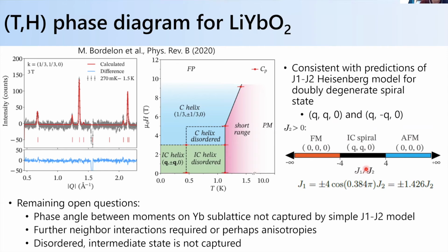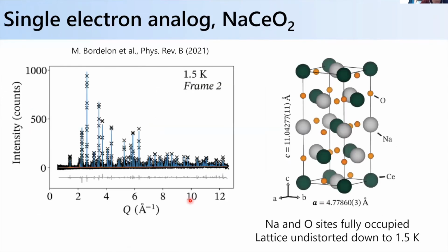And so in this regard, since we know the propagation wave vector, we can actually calculate where we should be on this phase diagram, which is where J1 should be equal to 1.426 J2. Okay, so this is sort of the minimal model. It doesn't capture everything, so it misses the phase angle between the moments on the two ytterbium sublattices, and obviously it doesn't predict this intermediate state that we saw, this disordered helical state.